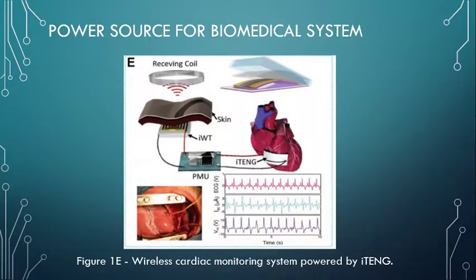Recently, Zheng and others developed a reliable encapsulation method of TENG, which provides the TENG outstanding stability in harsh environments. Based on this technology, the same group designed a novel iTENG, which significantly improved in vivo output and reliability. A keel structure was introduced to facilitate the contact and separation process of TENG in the complicated environment of a living body. Driven by the heartbeat of an adult Yorkshire porcine, the output voltage and current can reach up to 14 volts and 5 microamperes, which were improved by factors of 3.5 and 25 respectively, compared with the reported in vivo output performance of PENG and TENG.